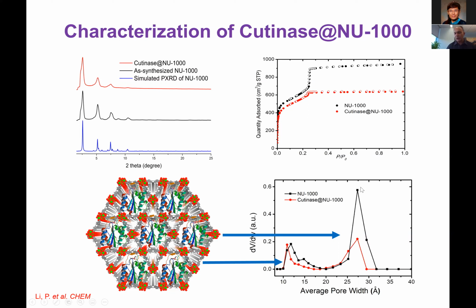And that's what you see in the bottom. Those are the pore size distribution. So if you take the black trace of the nitrogen isotherm and extract the pore size distribution, you will get the black trace in the bottom, and that shows that you have the hexagon and the triangle, the small and the large channel.